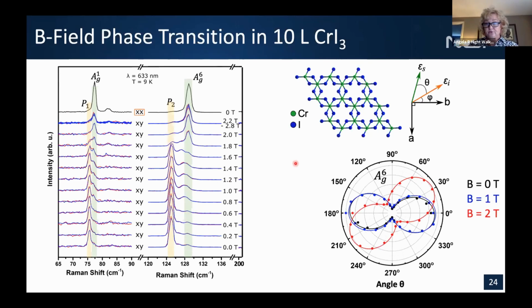Then we looked at the polarization, and this polar plot was really helpful for us. What we're seeing at 0 magnetic field versus 1 and 2 Tesla is a shift. So there is a phase transition happening of some sort, where you can see this angle is on the order of 30 degrees. I will say also at 9 Tesla, we did not see this polarization change again. So we see the shift, and then above 2 Tesla, it sits at that same location all the way up to 9.